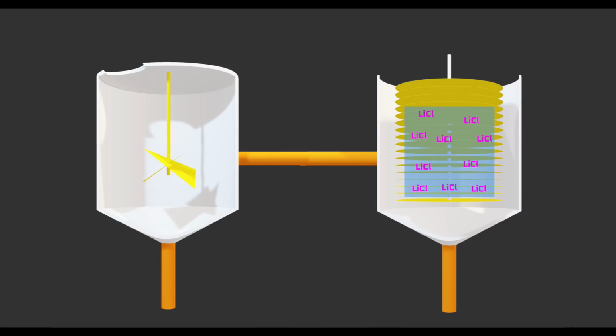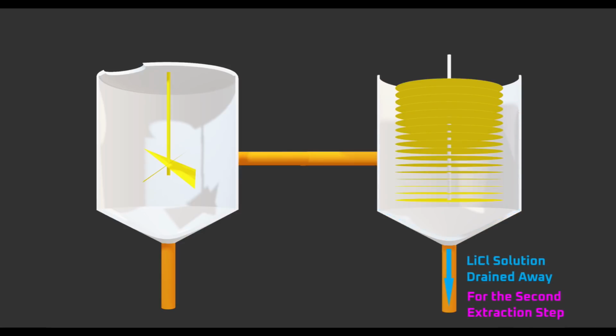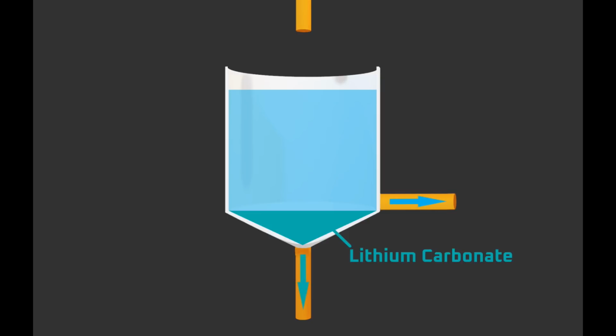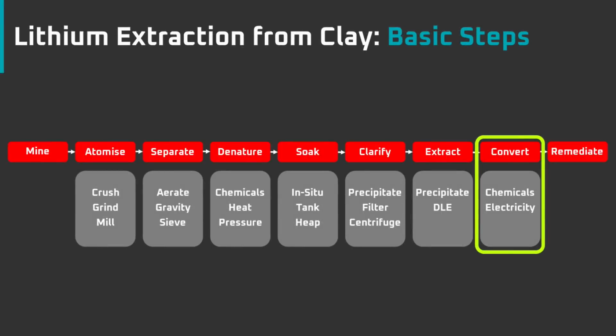This just leaves us with the lithium chloride-coated adsorbent, which would be flushed with a solution to release the lithium chloride into solution. That lithium chloride solution would be drained away to another tank for the second extraction step. In the second extraction step, the lithium chloride brine would be reacted with sodium carbonate, which would precipitate lithium carbonate from the solution. The water would be drained off for reuse, and the remaining lithium carbonate slurry would be dried to a powder for the conversion step. In the conversion step, the lithium carbonate would be reacted with lime to form lithium hydroxide, which is the final product Tesla would need for its cathode factory.